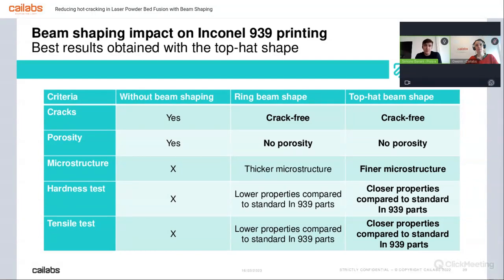And this consideration is valid both for the machine that we have used for printing in this project, so the EOS M280, but it's also valid for what we print with newer machines, for example, M290. In general, we observe cracks, and so following that, we perform hipping, for example, to remove that. Instead, we have crack-free both for top hat and ring beam. And then we have porosity without the beam shaping. Instead, here we have no porosity.